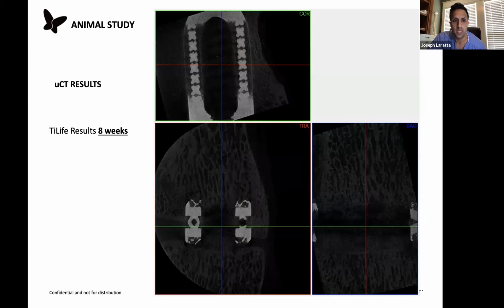and really no evidence of fusion or even early fusion at 8 weeks. Now, when you look at the TiLife technology, or this biomimetic technology, you can see that, again, there's not complete fusion through the cage yet, but you do see that there is bone that's forming already at 8 weeks and starting to traverse through the cage itself. And when you look at the microstructure of the bone, you can see that it's actually integrating in these pores relatively robustly on both sides of the cage. So there's early spot welding, which can lead to early stability for patients, that we could see already at 8 weeks on the MicroCT.